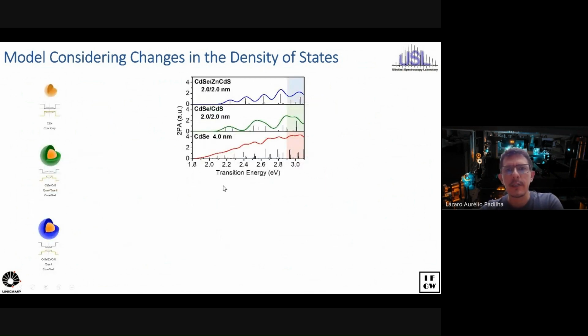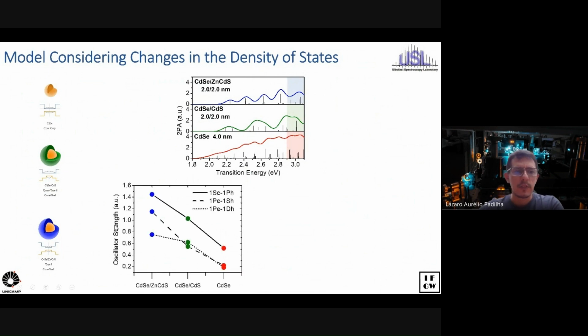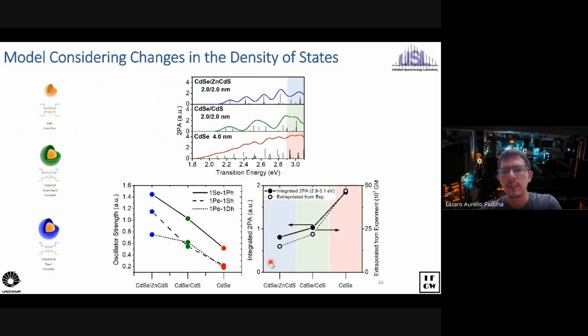More than that, if you look here and take the different types of structures and compare the oscillator strength of one transition and the total integrated area here on the quasi-continuum region, what you're going to see is that the oscillator strength for a single transition decreases when you go from type 1 to quasi-type 2 to core-only quantum nanostructure. However, for the integrated one, we see the opposite trend because of the changes in the density of states.